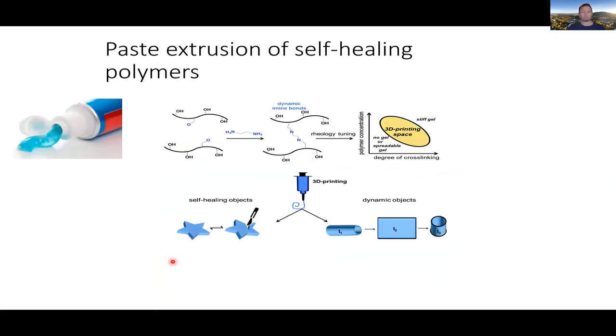So here is an example. Toothpaste: you squeeze it out and then it stops flowing. Essentially this is what this case is here. Here we have a paste polymer. In this case, it's a lightly cross-linked polymer. The key part of this, and I'm not going to go into too much detail, is that it's dynamically covalently cross-linked. So this imine can reverse, I should have a reverse arrow here. It can reverse back to free amine and free aldehyde.